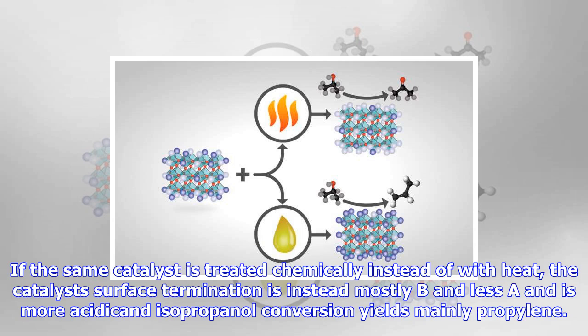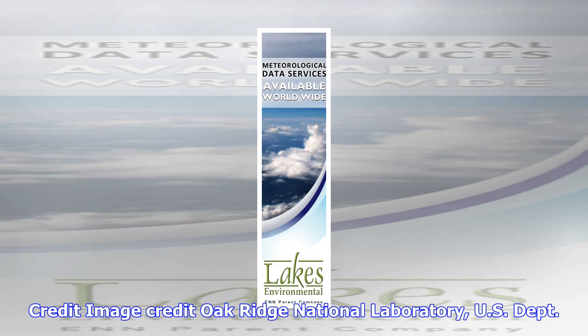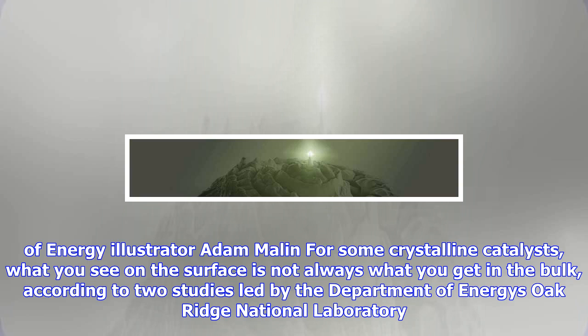If the same catalyst is treated chemically instead of with heat, the catalyst surface termination is instead mostly B and less A and is more acidic, and isopropanol conversion yields mainly propylene. Credit image: Oak Ridge National Laboratory, U.S. Department of Energy. Illustrator Adam Malin.